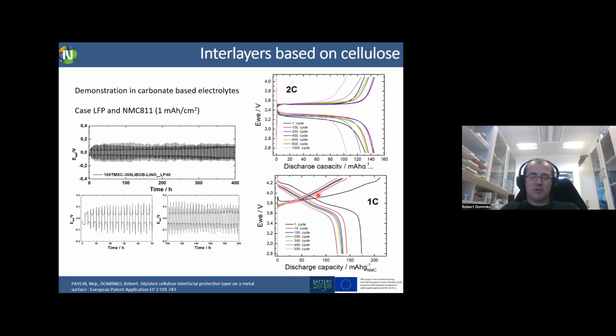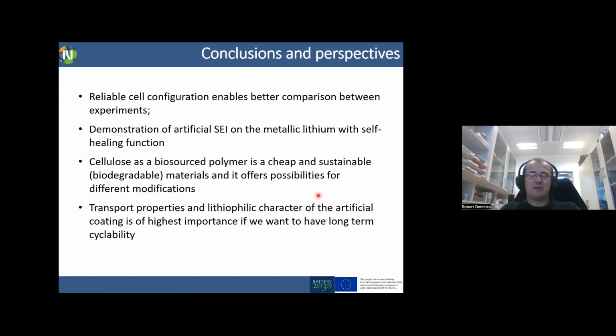NMC without problem, but of course it also depends on the quality of the NMC more than the quality of the coating. So it means that we can cycle. We never tried the high voltage lithium manganese nickel spinel, but we cycled this configuration of the elements of the cathodes. And with that, I would like to conclude my first part.